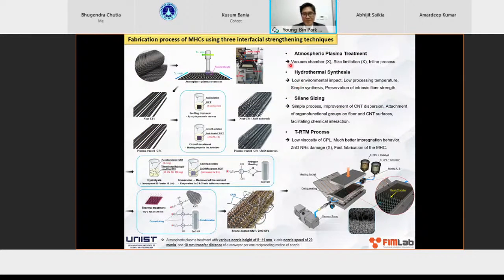Okay, I'm not going into great detail here, but again, we are treating the carbon fiber fabric, or woven fabric, with plasma first, and then we grow zinc oxide nanorods by using a conventional hydrothermal synthesis method, which is shown here. Then we create a solution containing the silane coupling agent dispersed with carbon nanotubes. In this case, we used functionalized carbon nanotubes. Then we dip the zinc oxide nanorod grown, plasma treated carbon fiber fabric in this silane solution dispersed with carbon nanotubes. And finally, we have fully functionalized and fully surface treated carbon fibers.